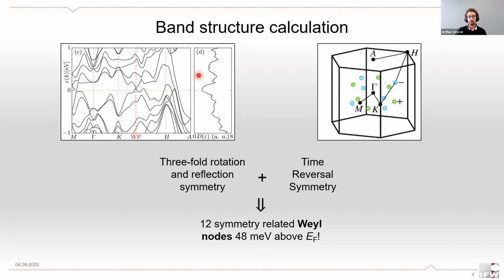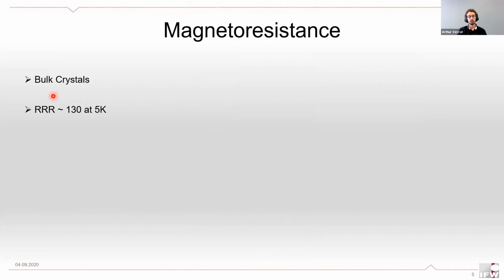So we wanted to investigate these materials using transport measurements. So the first thing that we did was to simply contact bulk crystals of trigonal platinum bismuth 2 and cool them down to about liquid helium temperatures. Doing this, we measured a residual resistance ratio (RRR) of about 130, which is a sign of good crystalline quality.